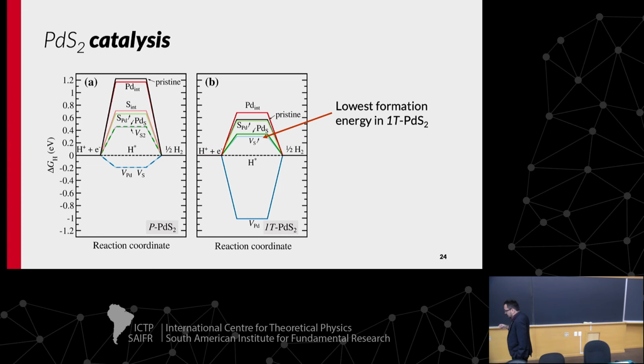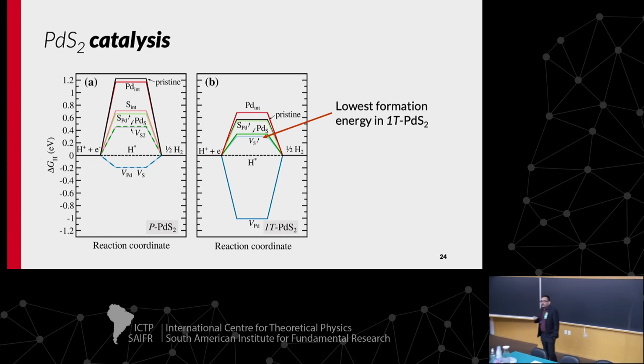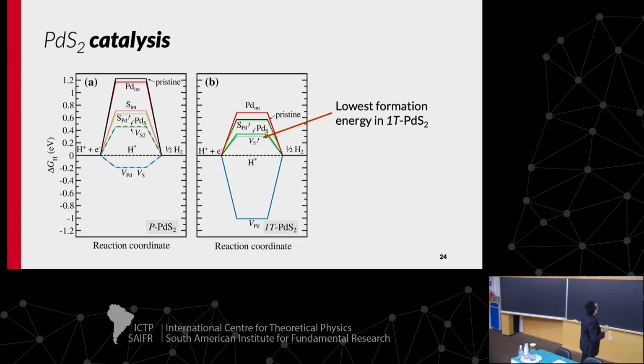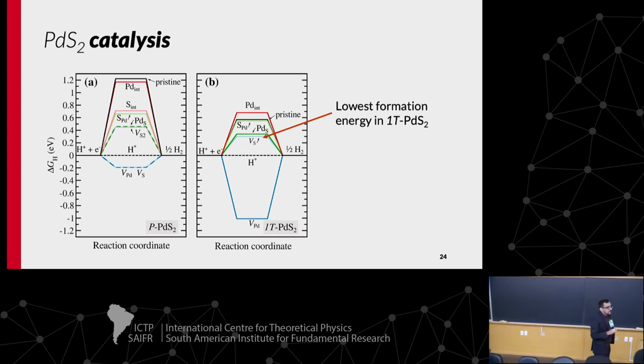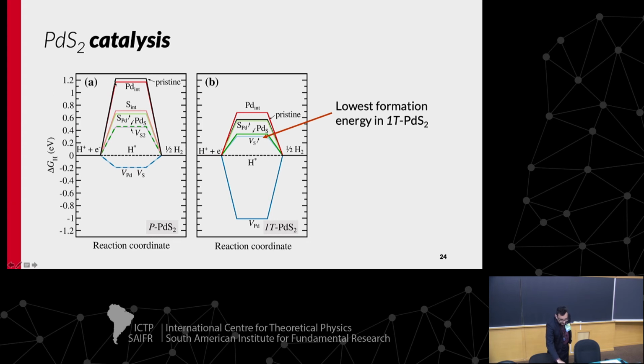When we calculate the hydrogen adsorption on the defects, first we compare with the pristine material, so no defects here, for the pentagonal phase and 1T phase. The 1T phase has a smaller delta G, so it's better than the pentagonal phase. But when you compare it with these defects in the pentagonal phase, all defects increase the catalysis for the hydrogen production, but not for the 1T. In 1T, some palladium vacancies or palladium interstitials have worse activity for the hydrogen production.